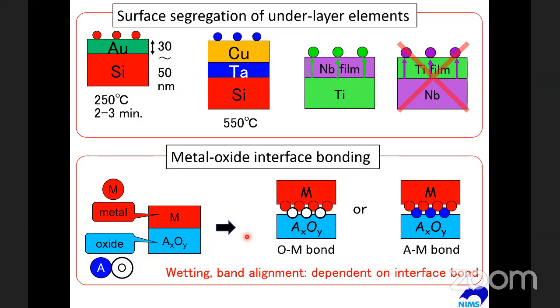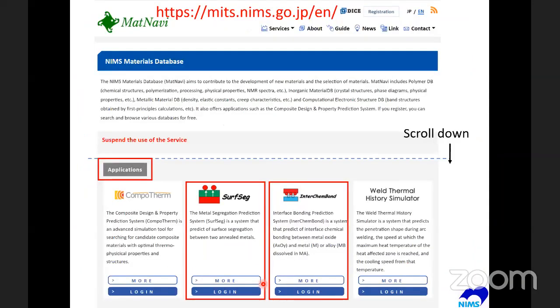The interface could be either oxygen at the interface or the metal atom at the interface. And this difference makes a huge difference in many properties like wetting or band alignment, which is a key to improve the power consumption of electric devices and so on. By this, segregation prediction or interface chemical bond prediction is